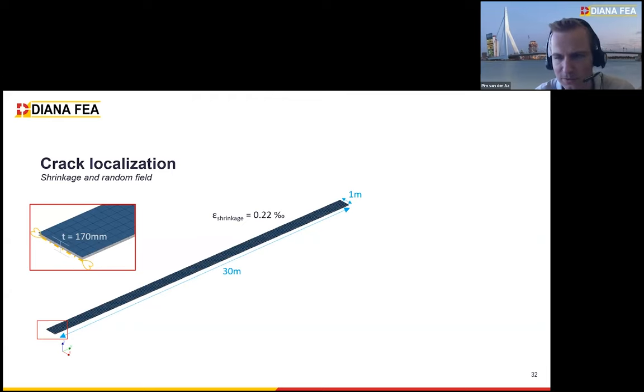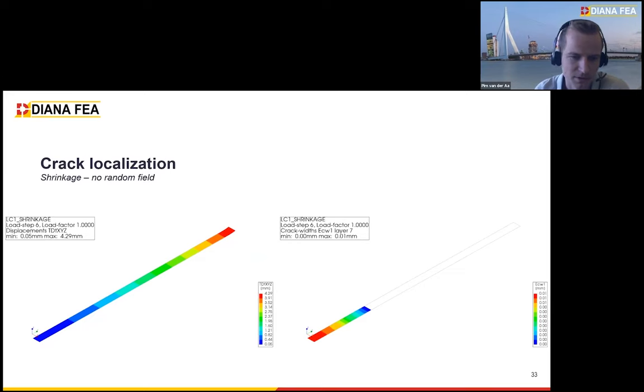We're going to compare the material without a random field, so that's just a homogeneous approach, and we're going to run an analysis with the application of a random field and see the difference. If we apply the shrinkage, we can see that the slab is shortening, in this case 4.3 millimeters. On the right side, you can see very small cracks, which are not localized at all. This is if we assume that there's no difference in tensile capacity between elements, so there's no random field applied.